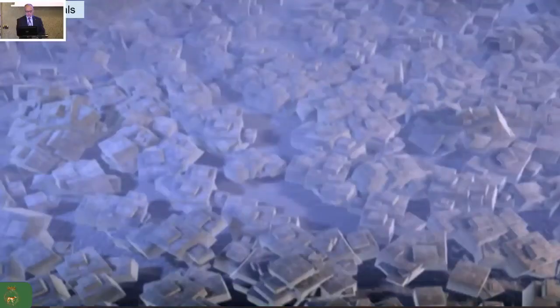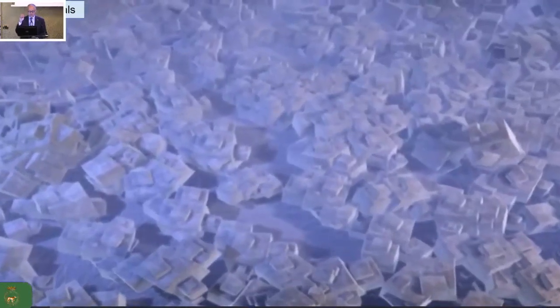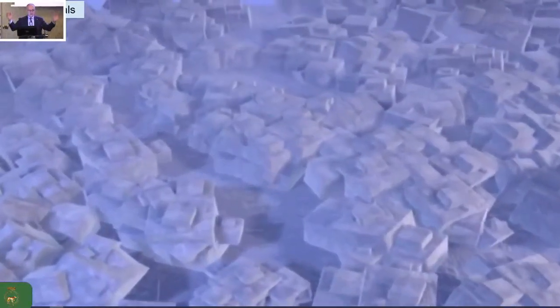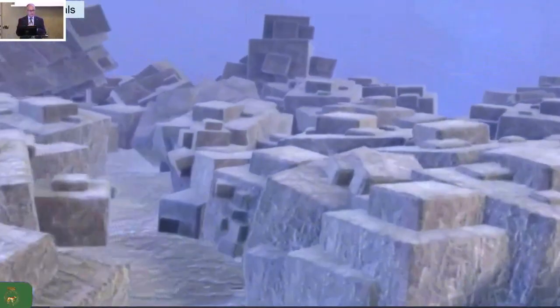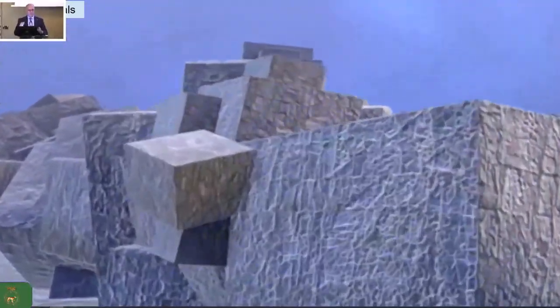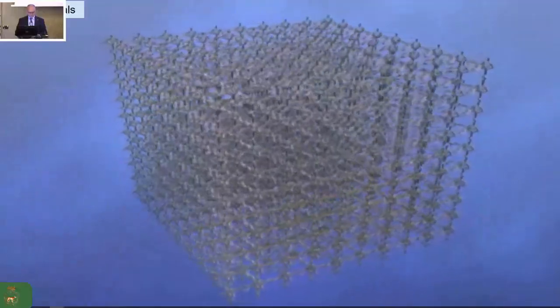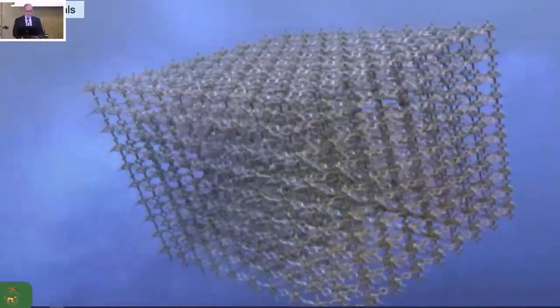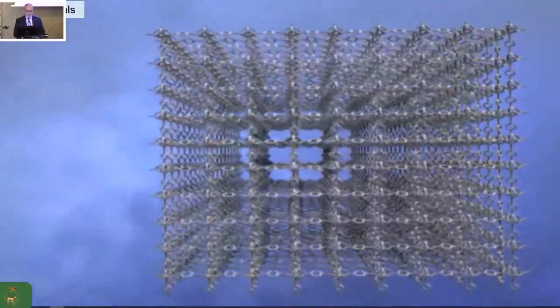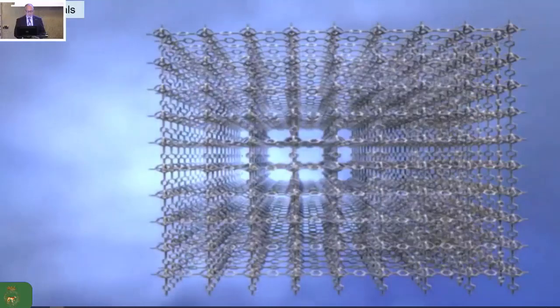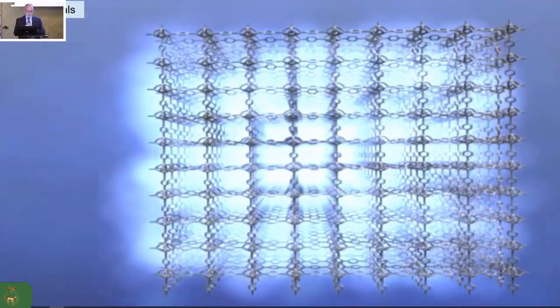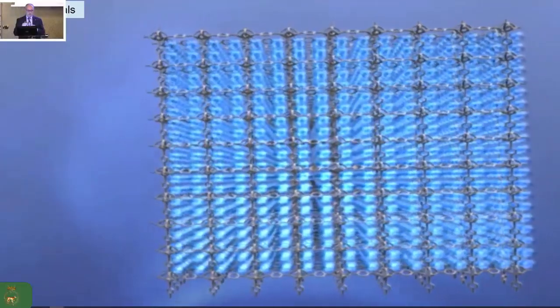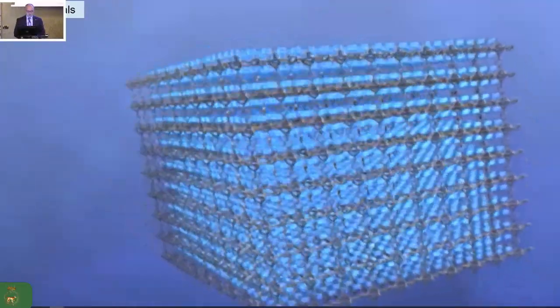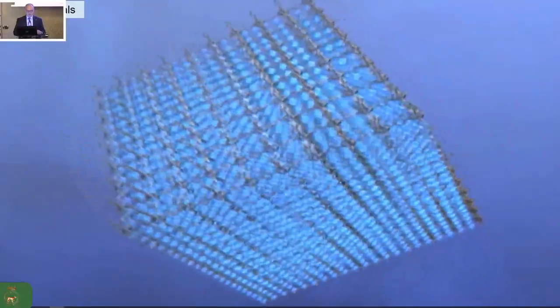Okay, this is why that happens: when you zoom in on each granule, it's almost like bees on a honeycomb. Instead of gases filling a very large volume, the attraction of the internal pores for that gas allows you to compress more gas per unit volume than you would without the MOF. So the MOF acts like a honeycomb for bees to assemble onto. And here you can see gases being compressed inside the pores by virtue of the interior of the pores being much more attractive to a gas than without the MOF.